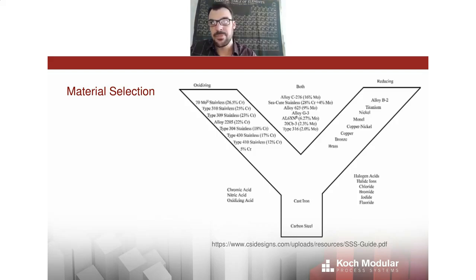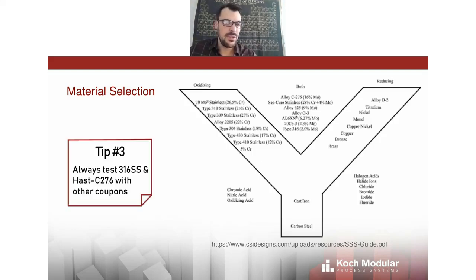It's quite common that corrosion rates won't be fully understood or won't be studied across many alloys. It'll sort of just resort to 316 and C276. So I recommend always testing 316 and C276 in addition to whatever else you're going to test. Test as many metals as you like, but don't leave those two out, because there will come a day where you're trying to find a particular fitting or a particular instrument or a 90-degree elbow with raised face flanges and a 300-pound pressure rating, and it's just not available in some of the lesser known alloys, but almost guaranteed you'll find it in 316 and C276. So test those always in addition to whatever else you're testing, so that you have some future options available when it comes time to build the system.